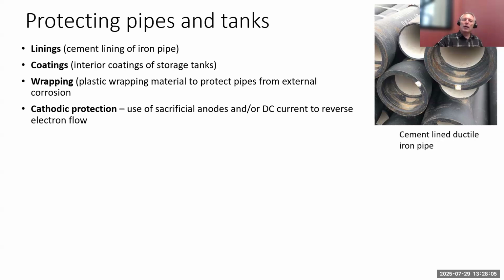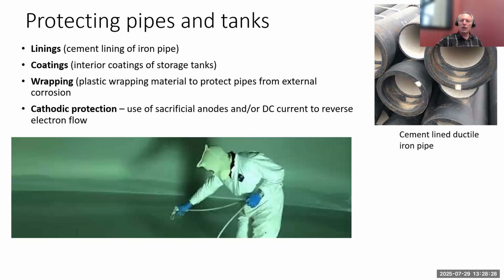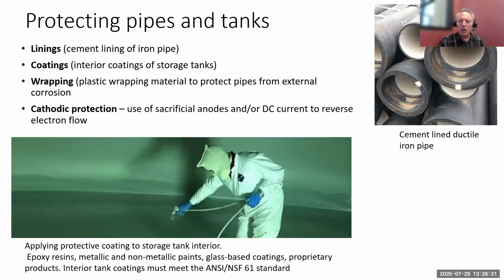There's also wrapping. I didn't get any images of that, but you can actually wrap the external part of a distribution main with a plastic material on the outside to prevent external corrosion. And of course, cathodic protection is the use of either sacrificial anodes or some kind of a DC current to reduce the electron flow, or both. Here's someone that's actually applying a coating to the inside of a storage tank. And there's different chemicals used, different materials used, I should say: epoxy resins, metallic and non-metallic paints, even glass-based types of coatings. And there's a bunch of proprietary coatings out there. They keep on improving in this area.